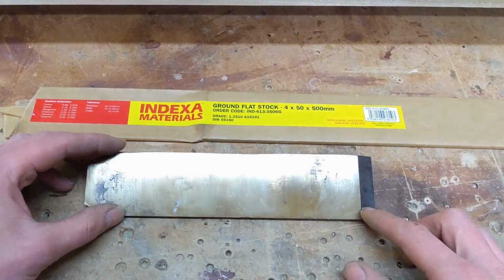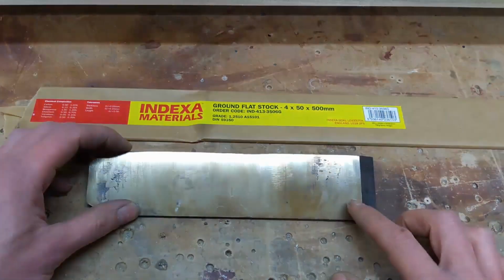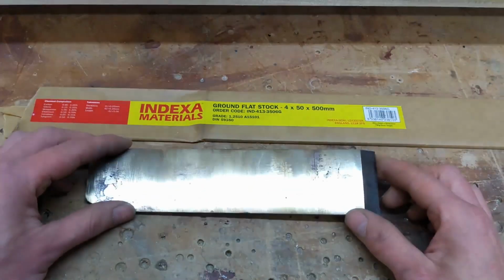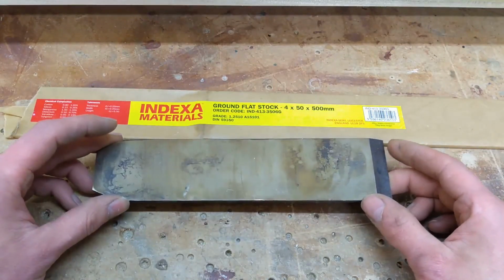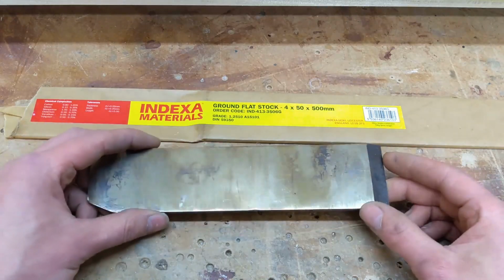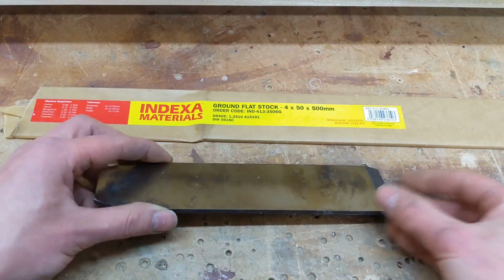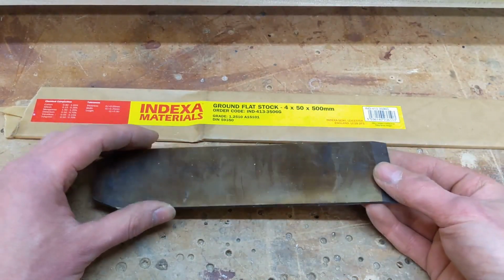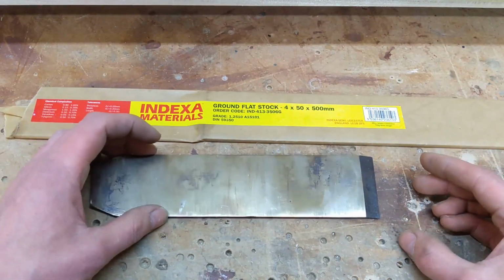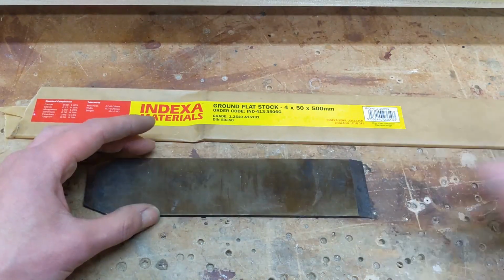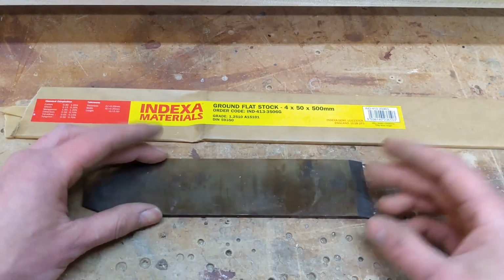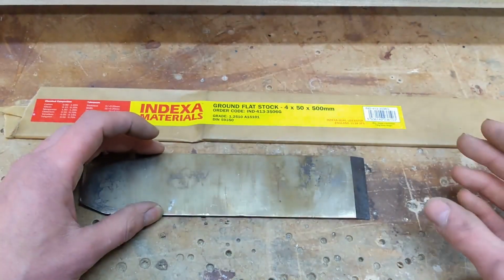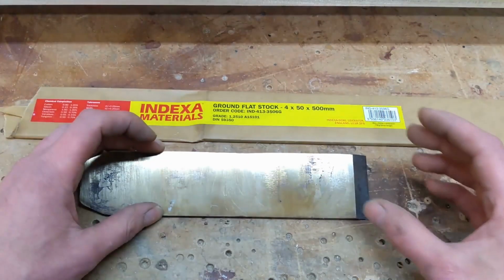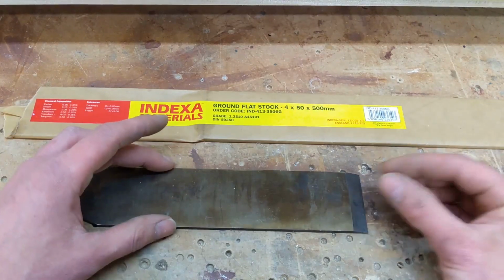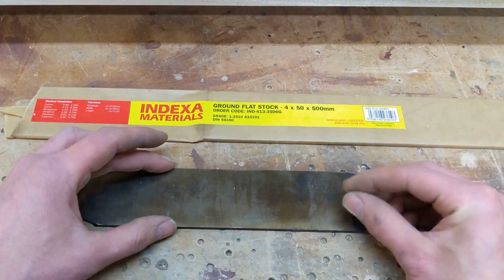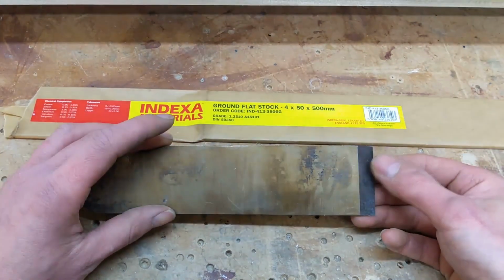Just a little bit more briefly about these blades, because it isn't my area of expertise, but from what I've learnt from making a few of these, I'm using O1 tool steel, and to get the best results from them, ideally they need to be heated in a controlled kiln to a set temperature, and you put them in for a set amount of time, and then quench them, and that gives you the best hardness. But from a DIY approach, you can get a perfectly usable blade doing it like I've done in a fire, as long as you bring it up to the correct temperature, and let it sit at that temperature for at least 10 minutes. You want to get it up to a dark orange, reddish temperature, and as long as it's lost its magnetism, when you draw the magnet to it, the magnet isn't drawn to it, and you quench it, you should get a usable blade.